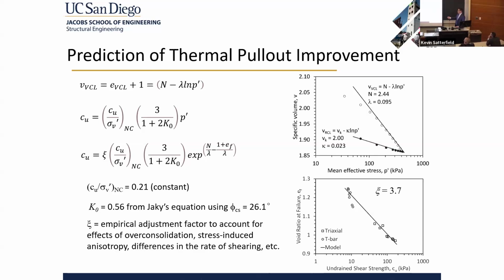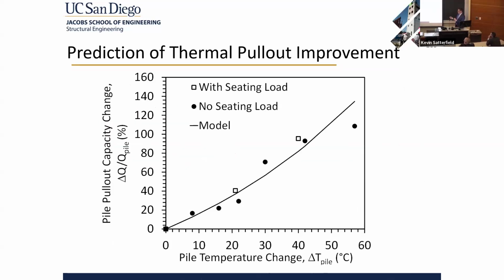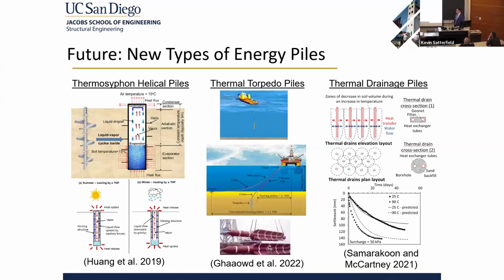But then we could take that shear strength and put it into our alpha capacity model, and we were able to get a very good prediction of our pullout capacity. So I think that that was a positive trend at the end, that we can use heat as a tool to improve the pullout capacity of these piles.